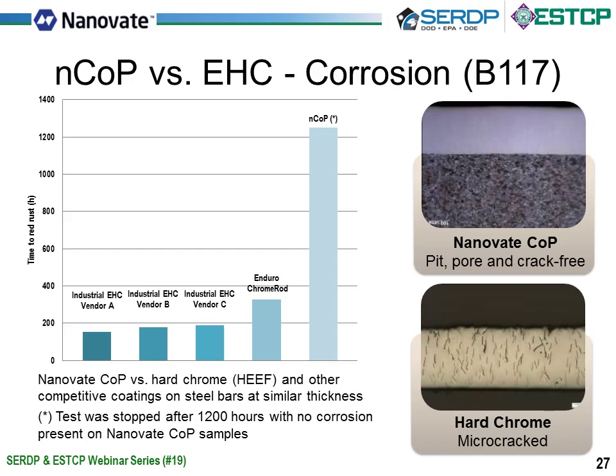So here's a slide that shows the time to red rust for various hard chrome materials compared to the nano-cobalt phosphorus. So you can see with the industrial vendors for hard chrome, you go to about just under 200 hours before you start seeing red rust. And then with a better process at Enduro, you can increase that to about just over 300 hours. But with the nanocobalt phosphorus, you can go well over 1,200 hours. In fact, no red rust was even seen on the sample, and this test was stopped after 1,200 hours.